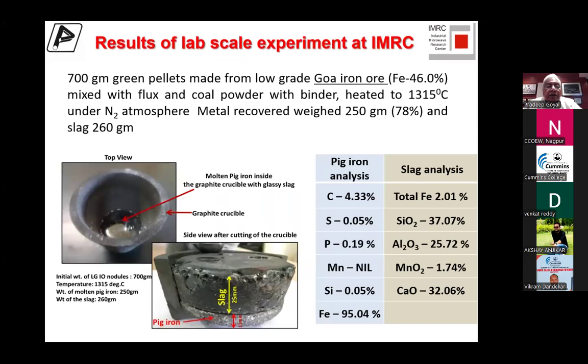Then we took a higher size. We took a 700-gram green pellet. Now we took the low-grade Goa iron ore. Here the iron content in the ore is only 46%, so a lot of it is sand and other materials. We did the same process, and here we were able to melt the iron at 1300 degrees Celsius, which is very low compared to what normally the iron is made.